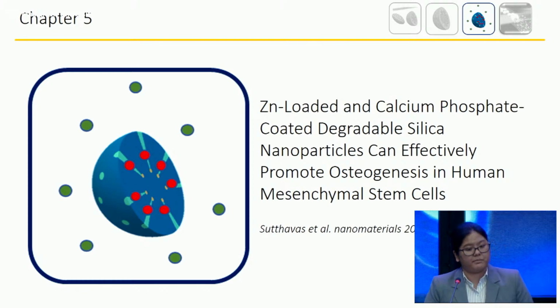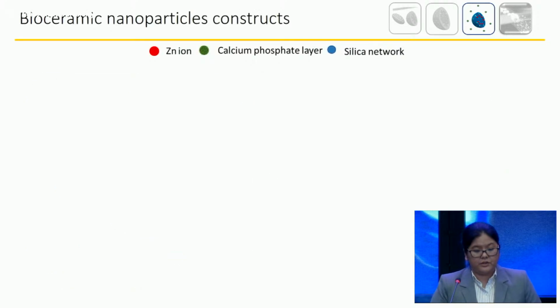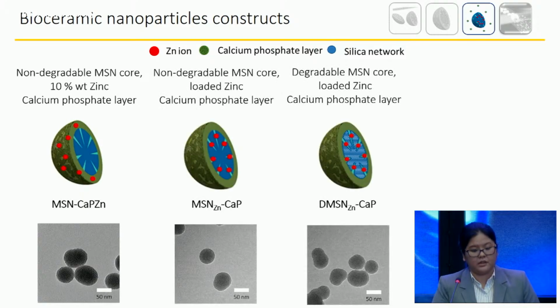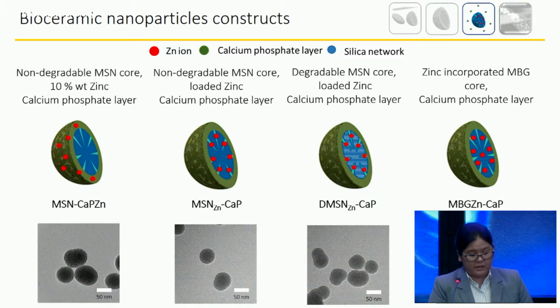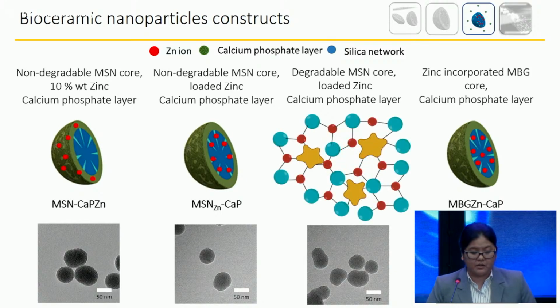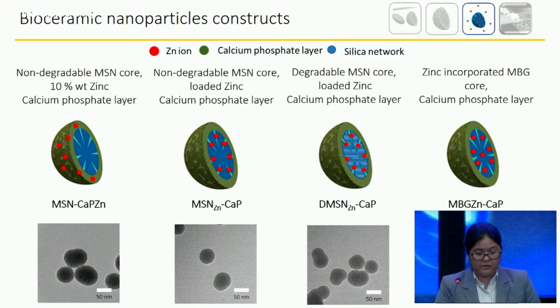Building on the knowledge gained from our previous study, we then investigated the importance of incorporation on the bioactivity. Using zinc as a representative osteogenic ion, we investigated zinc incorporation on the surface, in the mesopore, and in the matrix. Moreover, we created a biodegradable mesoporous silica nanoparticle, or MSN, to investigate the importance of the mesoporous silica nanoparticle degradation and their activity. The degradable silica matrix was created by addition of an impurity into the silica network during synthesis. The mesoporous bioactive glass was obtained from our collaborator.